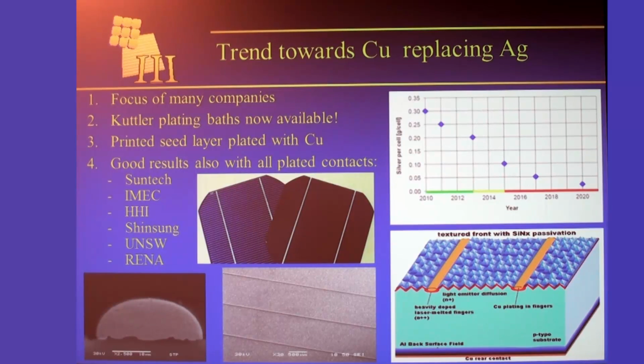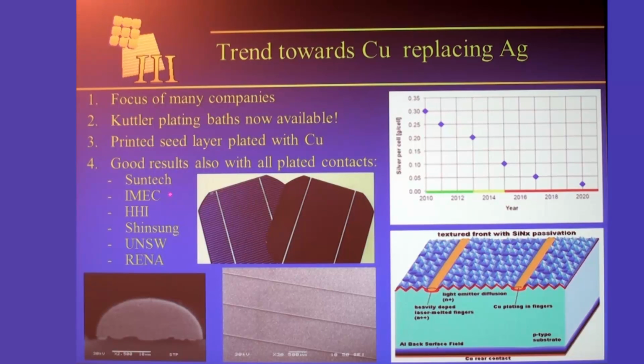The other direction is just using all plated contacts. And I guess this is our preferred approach here at this university. We've developed some nice technology here that gets used on the Pluto technology. So this shows a schematic of a Pluto cell, and these are all metal plated contacts. And more than 99% of that metal there is copper. So that's our preferred approach, but we've also seen good results from IMEC, Hyundai, Shinsung, UNSW, Suntech, RENA, all presenting good results on all plated contacts. Often people put down nickel initially because nickel, for a range of reasons, is a very good interface to the silicon. But then plate copper on top of that to be the main conductor, because copper actually has pretty much the same conductivity as silver does.